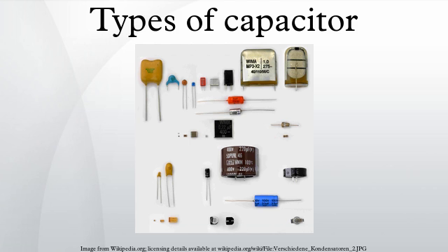In V per microsecond, the permissible pulse current capacity of a metallized film capacitor generally allows an internal temperature rise of 8 to 10 kelvins. In the case of metallized film capacitors, pulse load depends on the properties of the dielectric material, the thickness of the metallization and the capacitor's construction, especially the construction of the contact areas between the end spray and metallized electrodes. High peak currents may lead to selective overheating of local contacts between end spray and metallized electrodes, which may destroy some of the contacts, leading to increasing ESR.